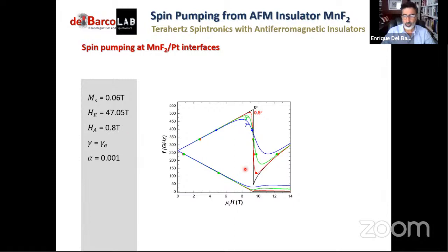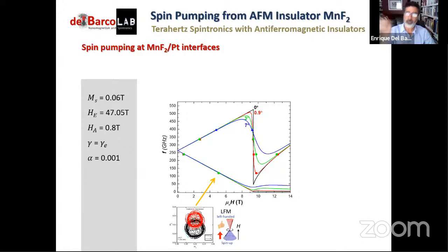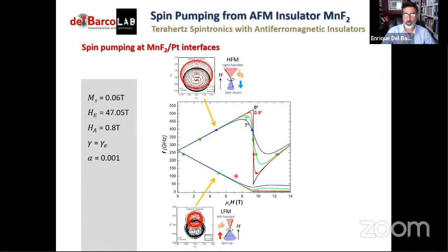I want to show you a little bit about the dynamics of the spins when we drive the system into antiferromagnetic resonance. When you look at the low frequency mode and you look at the trajectories that the sublattice magnetizations describe in these cases, you'll see that the trajectory of the sublattice magnetization that is aligned with the magnetic field is smaller than the one that is anti-parallel to the magnetic field. And if you go to the high frequency mode, you will actually see the opposite. And that's why one goes down, the other one goes up, because the resulting magnetization is anti-parallel to the magnetic field in this case, and parallel to the magnetic field in this case, right?